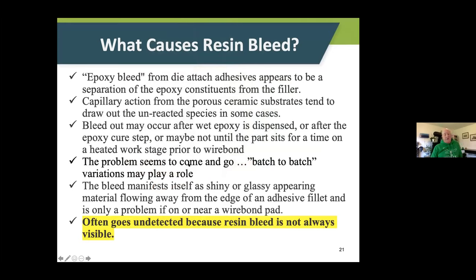So what causes resin bleed? Well, it's basically, you know, separation. Now this usually shows up after it's been cured and maybe is sitting on the stage of the wire bonder. Sometimes it happens before you even put it in the cure oven, or you see it after you pull it out. But you're separating out some of the resins that weren't reacted as part of the crosslink that occurs. And for some substrates, you know, the theory is the porosity in the substrate actually draws the resin out. So bleed out may occur after the epoxy dispense or after the cure step.